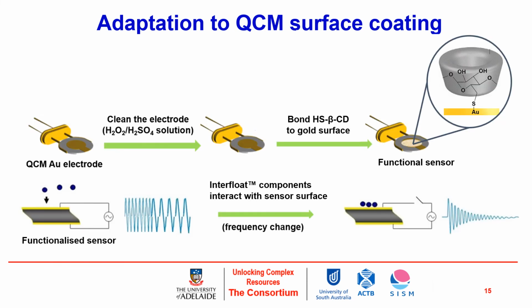With this material in hand, we're now at the point where we are functionalizing a QCM sensor. So to date, what I've achieved is binding these components to the gold surface and confirming that that sulfur-gold covalent bond has been formed. And I'm beginning to assess how these materials on the surface interact with Interfloat components in solution through using QCM experimentation.